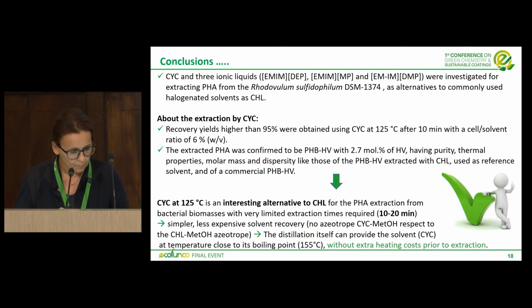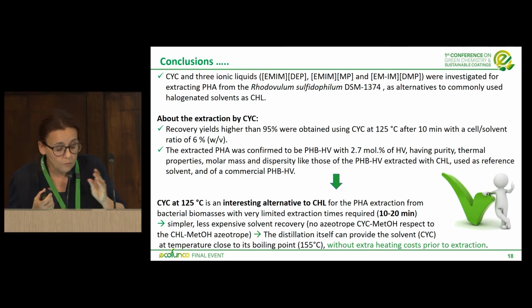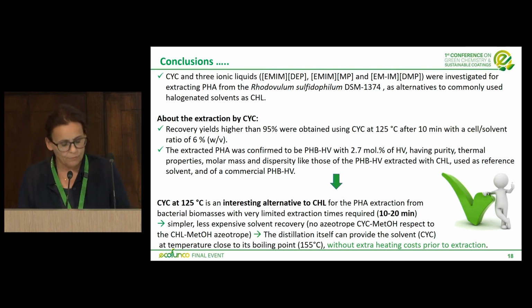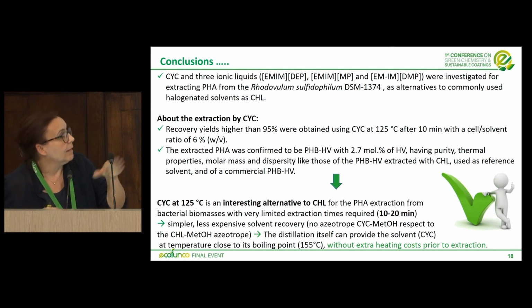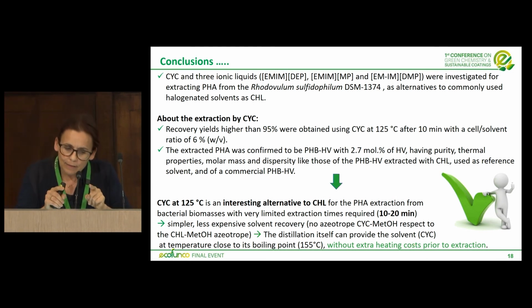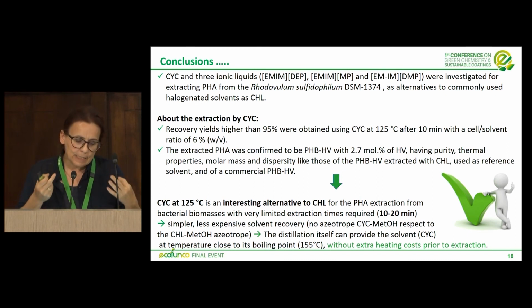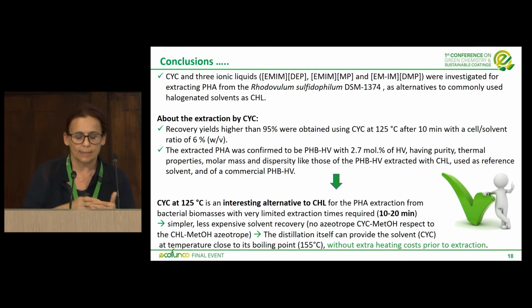material. Okay, in conclusion, on the very good results obtained with the cyclohexanone, we can say that the cyclohexanone at 125 degrees is a very interesting, potential alternative to the chloroform for the extraction of PHA from bacterial biomass, with very limited extraction times required, about 10-20 minutes, and in addition, the recovery of the cyclohexanone from the mixture of cyclohexanone and methanol is simpler and less expensive